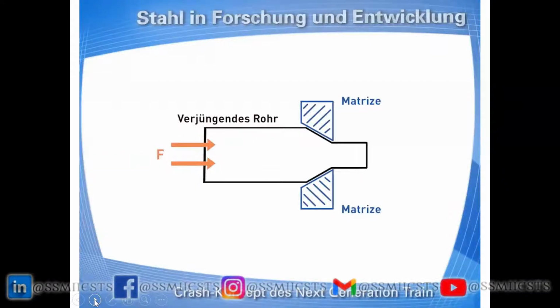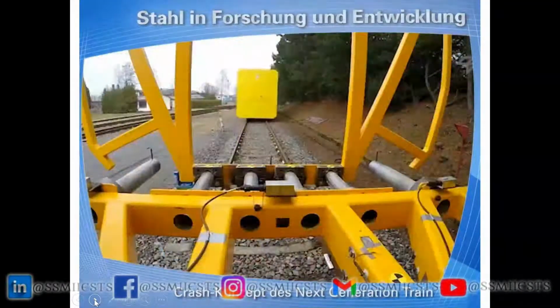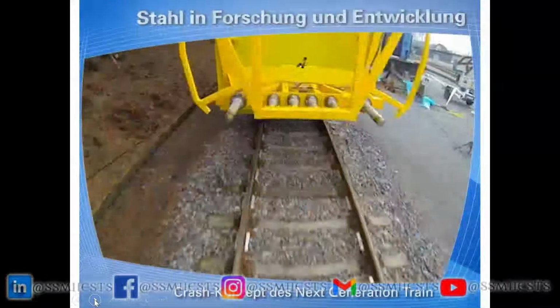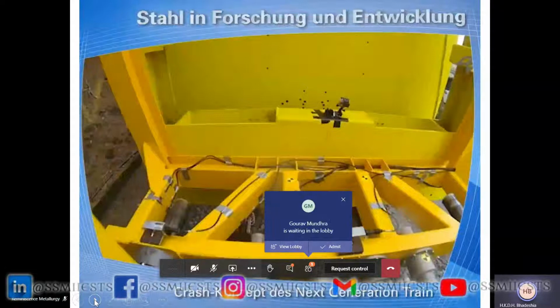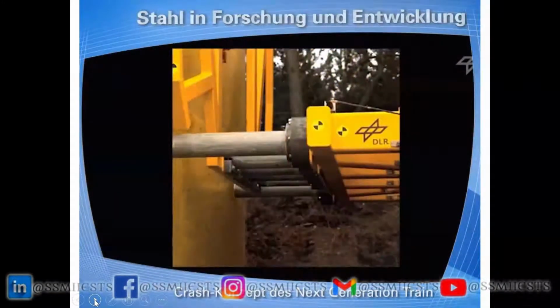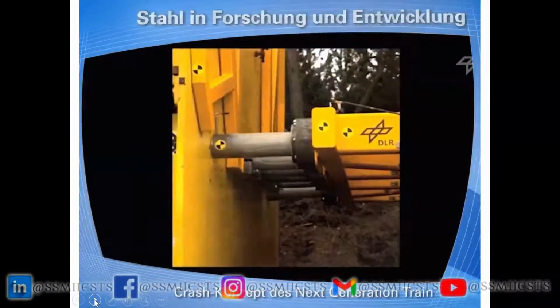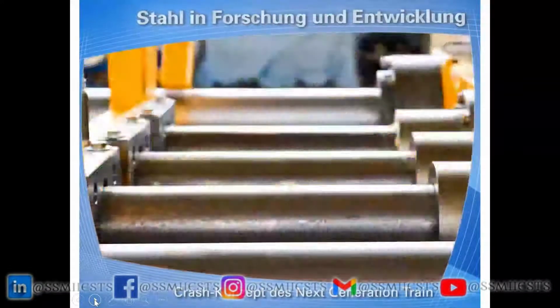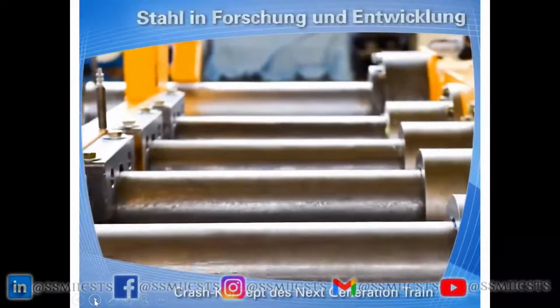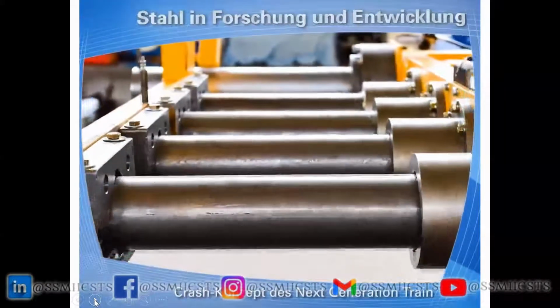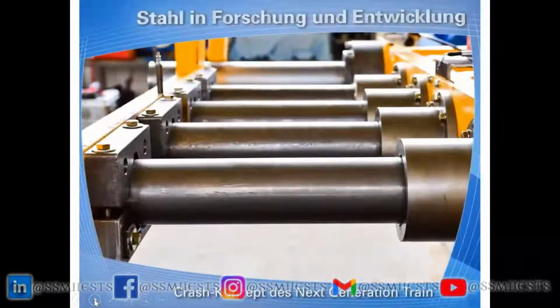Okay, so this is showing the extrusion of the cylindrical component, and this is an actual crash test. So you can see those cylindrical elements which are made from TRIP steels, they are actually being extruded into much smaller diameter during the crash. And that is giving uniform deformation, and therefore you exploit all of the stress strain curve of the TRIP steel. Okay, next slide.